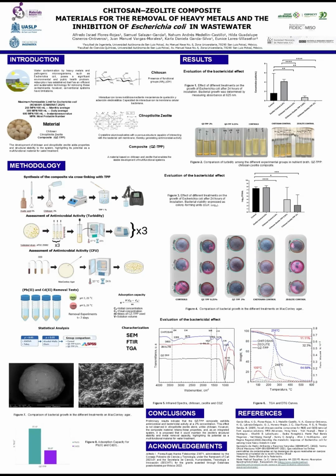Results: antimicrobial activity. The results indicate that the antimicrobial activity of the evaluated composites is primarily determined by the presence of chitosan. The 2% composite showed inhibition of E. coli growth comparable to that observed in the chitosan control, both in terms of the decrease in absorbance and the reduction in the number of CFU, demonstrating that its incorporation into the clinoptilolite matrix and subsequent cross-linking with sodium tripolyphosphate did not significantly affect its antimicrobial properties.